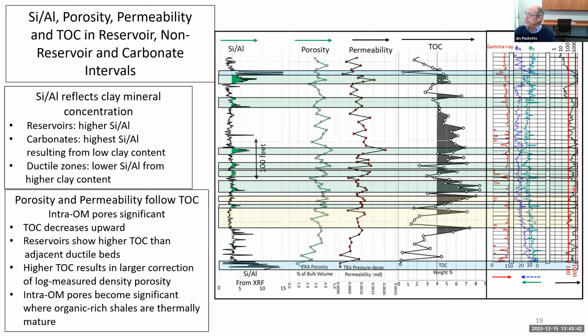Now, that may not hold true if we start to get into really tight carbonate intervals. But in these mud rock intervals that are silty claystones or clay siltstones for the most part, when we see that high resistivity, and then if that high resistivity is coupled with increasing gamma ray, which might be reflecting our TOC, our organic matter content, then I start thinking, well, we probably have some organic porosity in here, intra-organic porosity, and it's contributing to some of this better porosity and permeability we see in the permeability and the porosity curves in the middle of this figure.